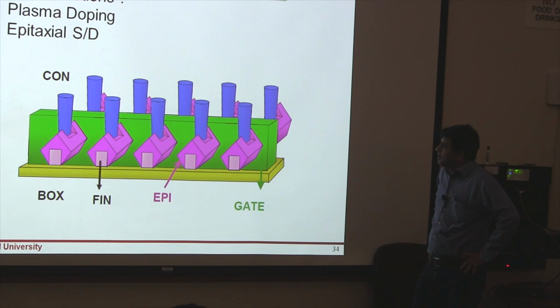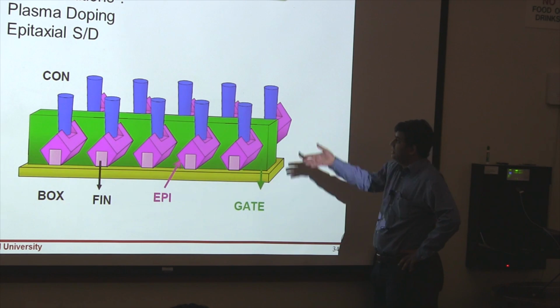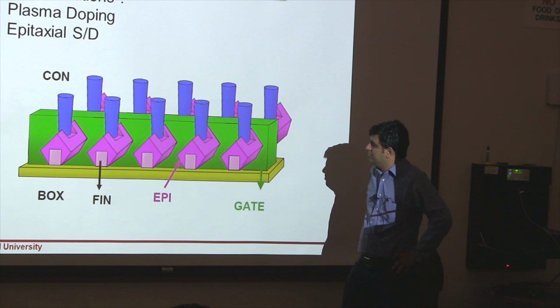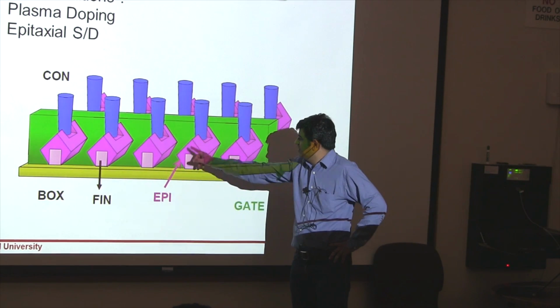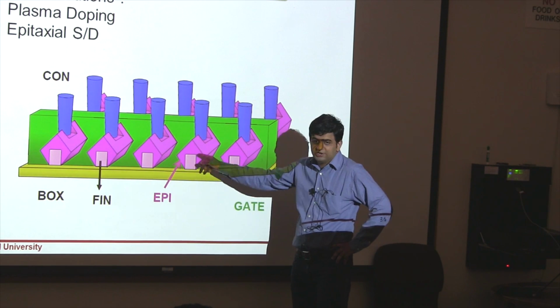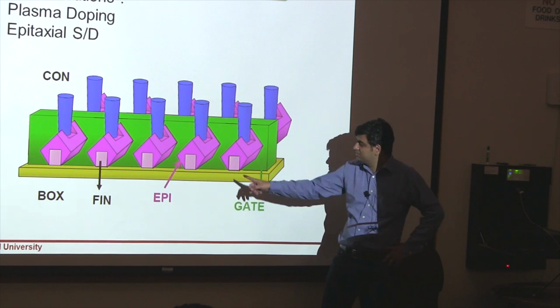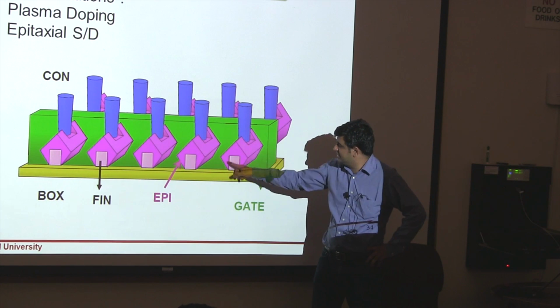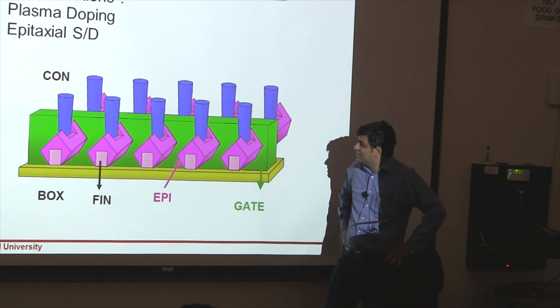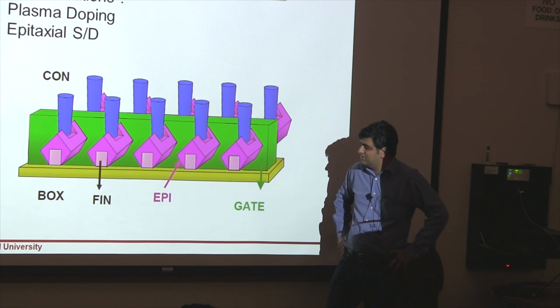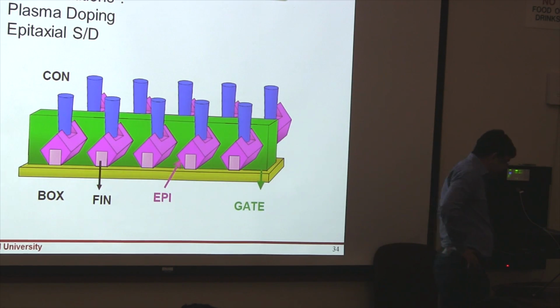So one way to get around it is to use a doping process which is conformal. So use a plasma instead of an ion implant process, which is less directional, to do your implant, or you can make these junctions by doing epitaxial growth of your source drain. So remember that picture you were asking about, what was that other picture? That was that epitaxy, and it looks like this diamond when it grows around this fin, and that's one way to get around this junction problem. But all these problems arise because of this 3D nature of your fin, and that's why it's so hard to make this device.